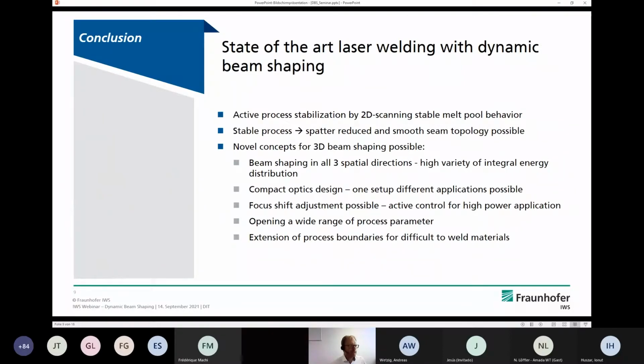Yeah, and at the end, I would like to conclude shortly. I think what is possible right now is that we have a lot of processes where we actively stabilize the process by 2D beam oscillation. And this is also shown by some weldings for aluminum die-cast material, which is already in the industry. And therefore, we are using the 2D beam oscillation quite successfully with reduced spatter and smooth seam topology.